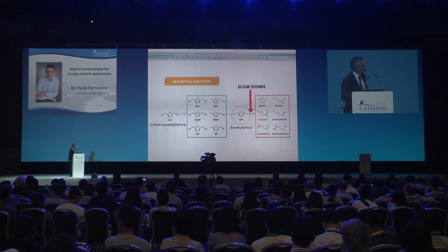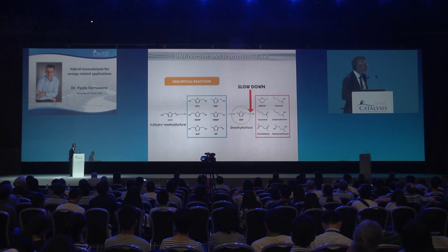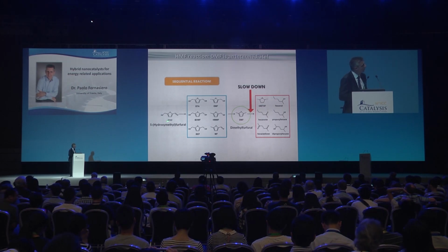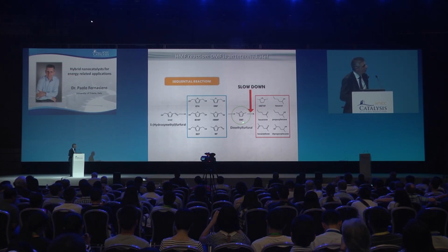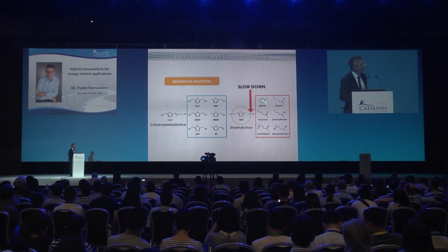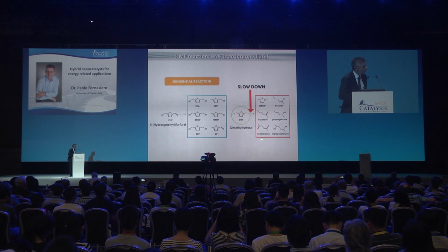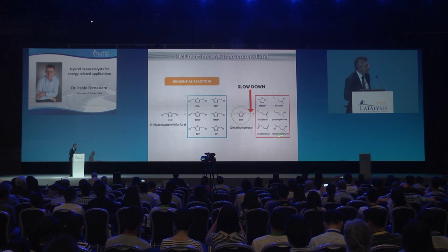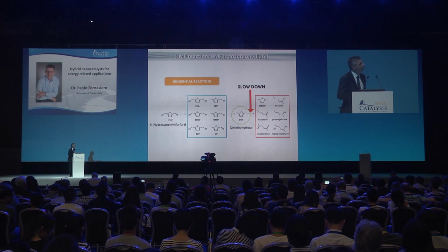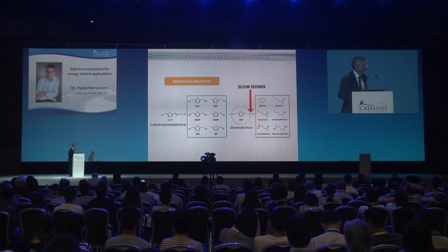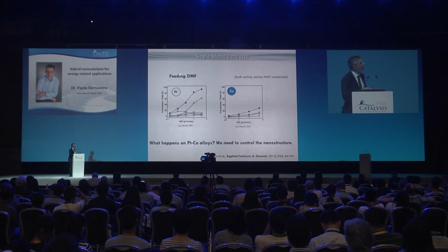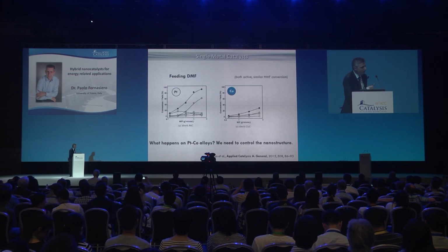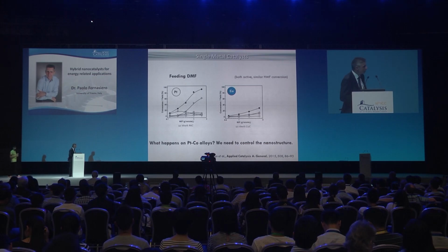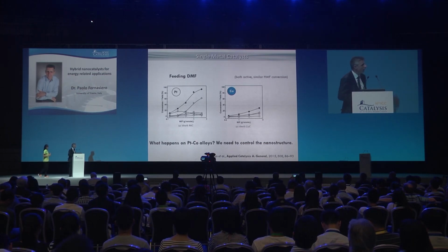And we were very much interested in the reaction HMF to DMF, but of course the catalyst which can transform these two also promotes sequential reactions, like those that lead to the production of these products in red here. So if you want selectivity, you have to slow down this type of reaction. But if you feed DMF on the catalysts that do the first step, like platinum and cobalt, they, of course, are still active. So we were interested in seeing what a platinum-cobalt alloy can do.